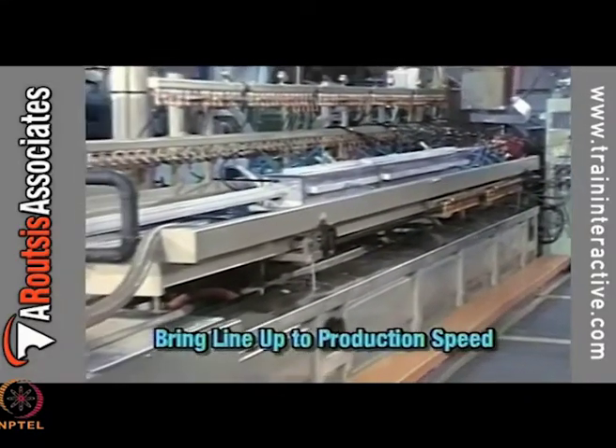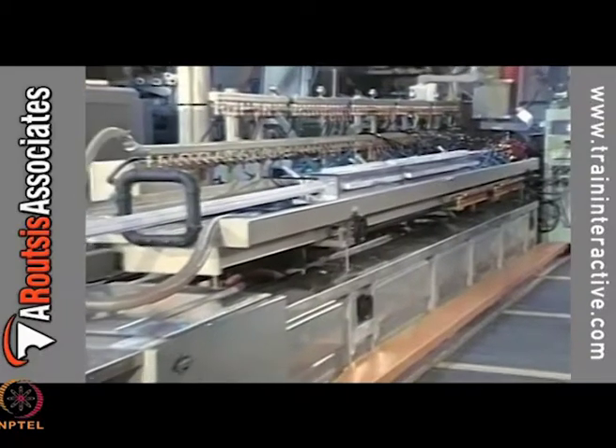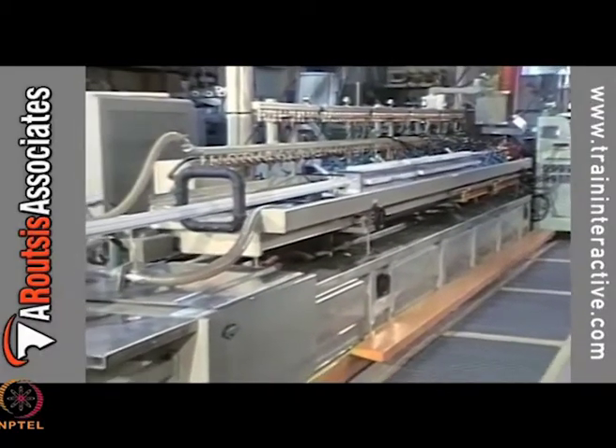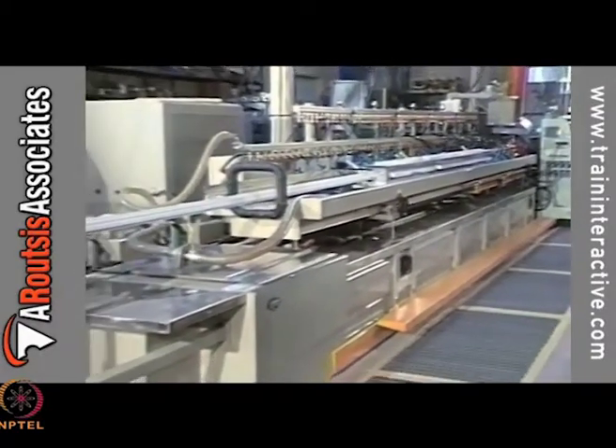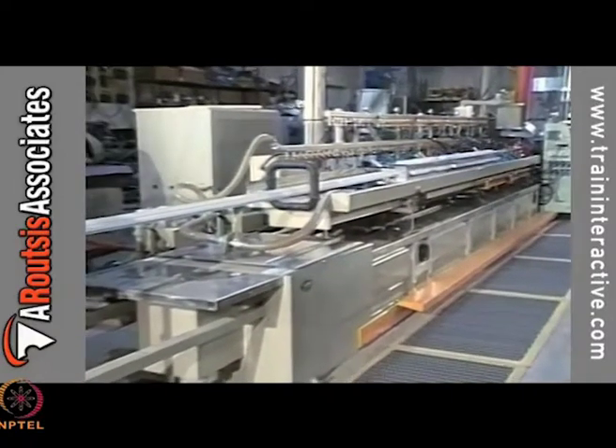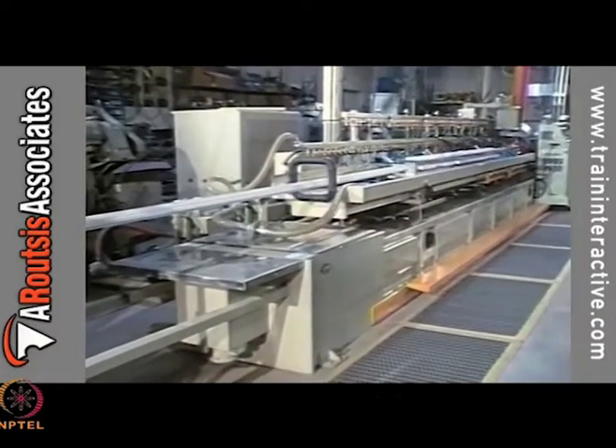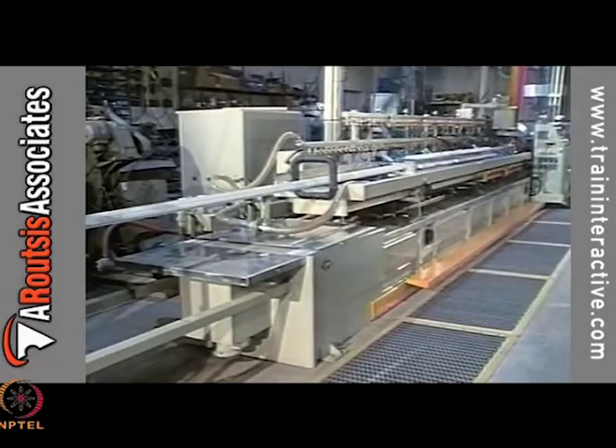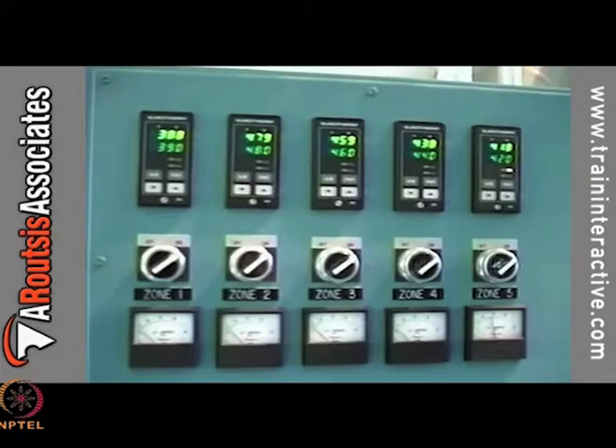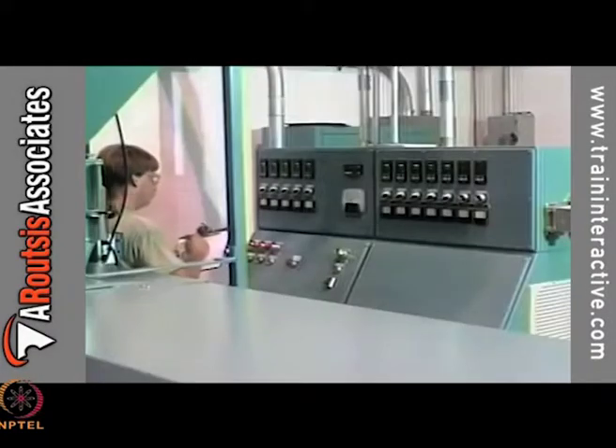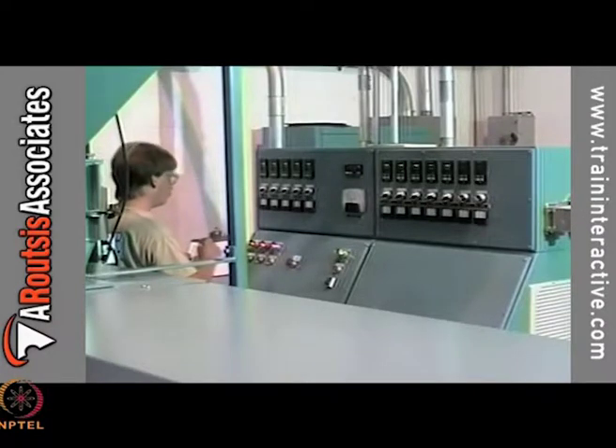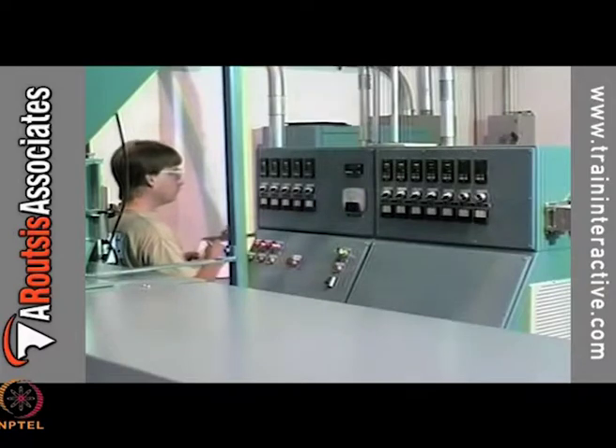Because it may take a large extruder as long as 2 hours to achieve consistent temperatures, continue to monitor closely until the process is stabilized. Don't make changes to the settings unless you are certain the process has stabilized, unless those changes are part of the procedure. Take the readings that are called for by the standard operating procedures or operator instructions and check them against the run sheet or setup sheet.